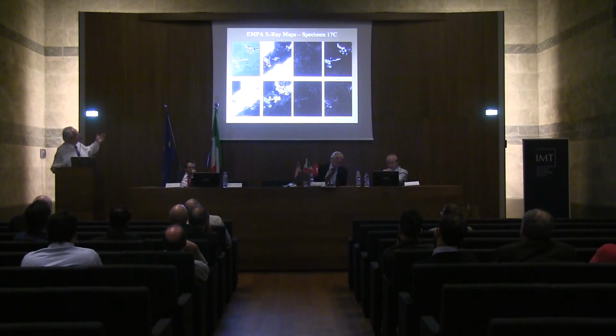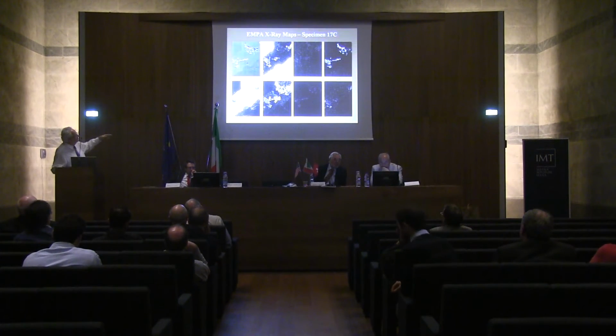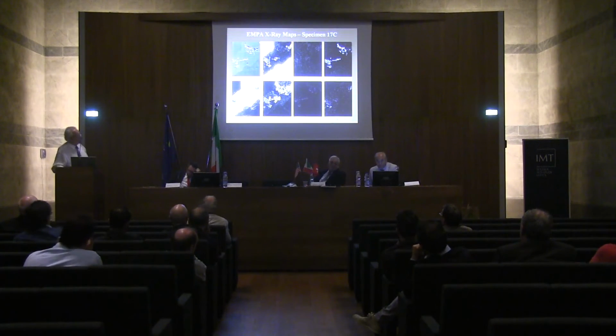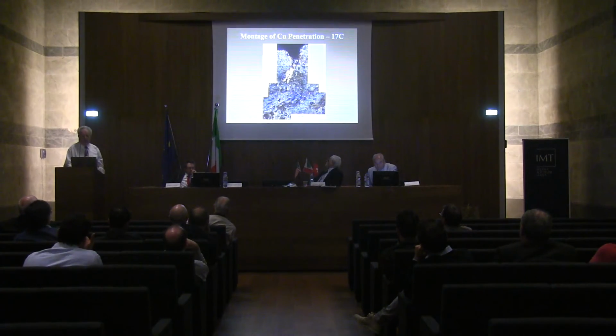And then here's some additional mapping at higher magnification in the electron microprobe, which was better for mapping in those days especially than the EDS in an SEM in those days. And you can see, look at all the copper in the lower left. I mean, and the iron is not in that zone. A little bit in there, but not much. There's tin in there, a little antimony, a little bit of zinc. There's lead in there. And of course there's some oxygen, but not a lot.